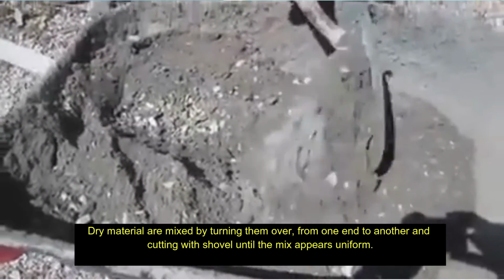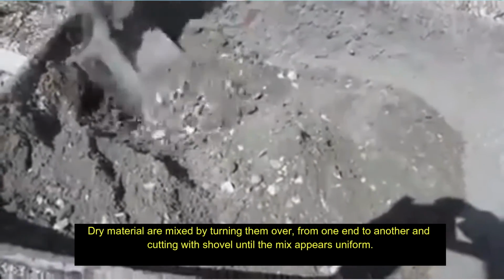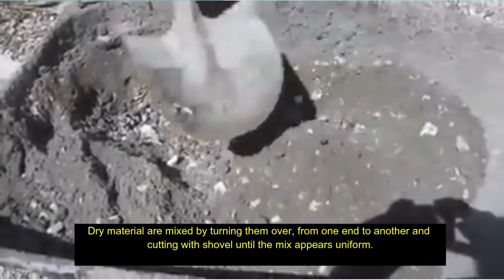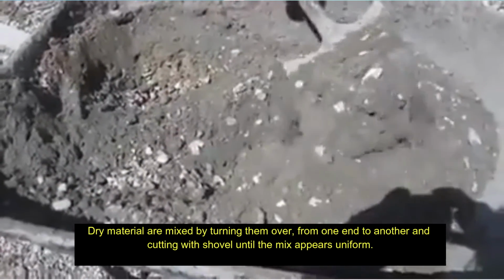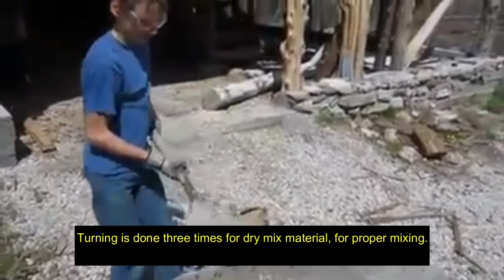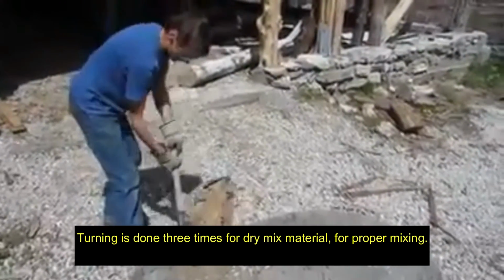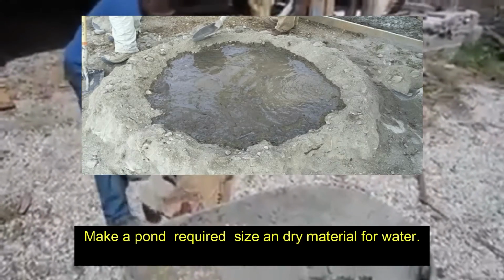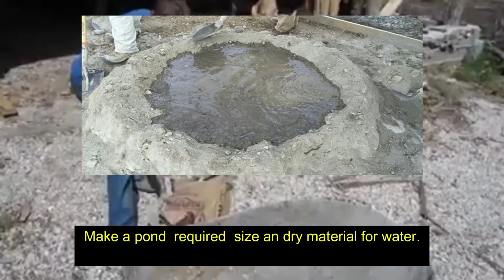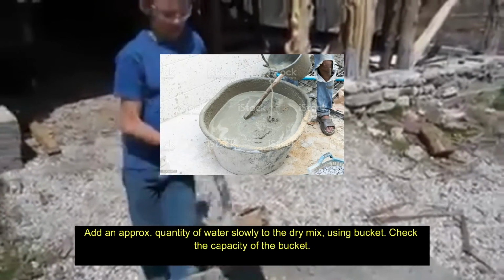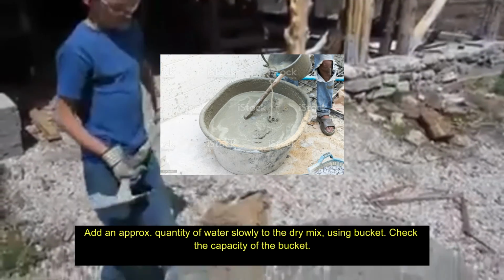Dry materials are mixed by turning them over from one end to another and cutting with a shovel until the mix appears uniform. Turning is done 3 times for the dry mix material. For proper mixing, make a pond of the required size in the dry material. For water, add an approximate quantity of water slowly to the dry mix.